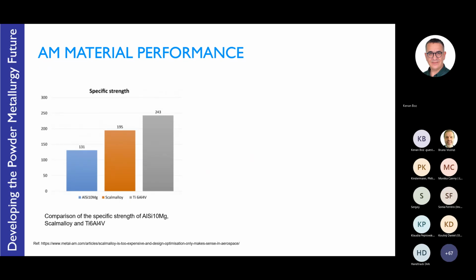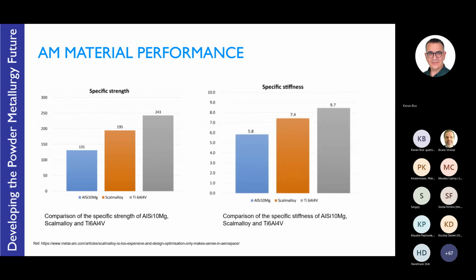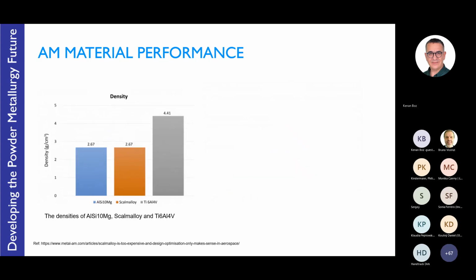Here we have an aluminium alloy, a relatively new alloy, Scalmalloy, and comparing to titanium 6-4. So specific strength, titanium has the advantage. And likewise, when it comes to specific stiffness, titanium has the advantage here also. And then if we compare density, however, aluminiums, of course, have a lower density compared to titanium. So you have to take all these factors into account when you're designing components.